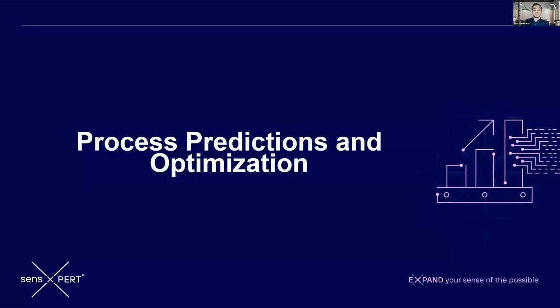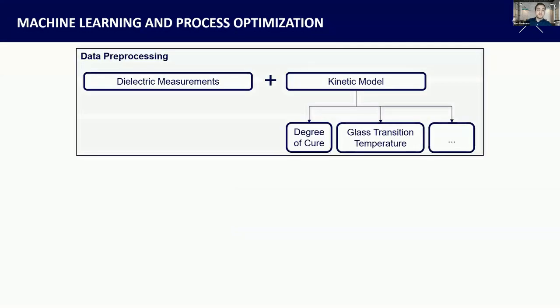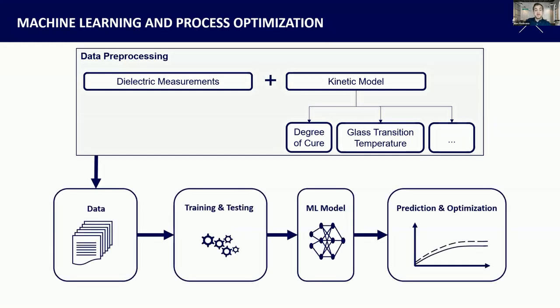And so that comes to really the next step of this, where we implement the machine learning into our edge device. And with our cloud service, we can make constant adjustments to that. And so we start again with dielectric measurements, and we combine the dielectric measurements with the kinetic model, so we have real material understanding. And that's our pre-processing data. So that's the data that we use to really train and test. We create our models, and then we can get predictions and optimizations.